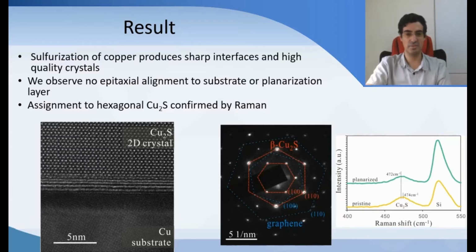And we see that graphene is not aligned epitaxially with the copper. So that's strange. The other strange thing is that we're getting hexagonal copper sulfide, and that's different from if we just grew without the graphene layer. So the graphene layer is doing several things.